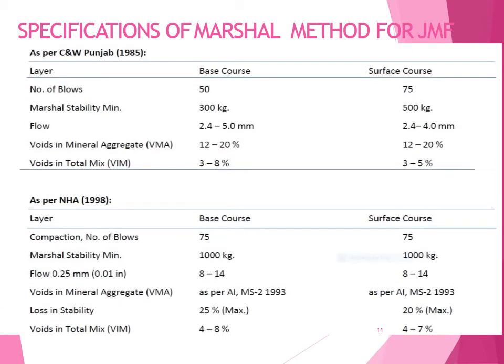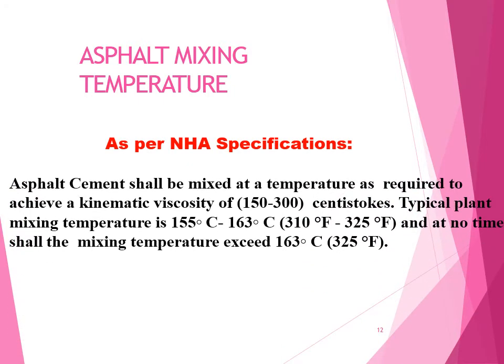Specification of the Marshall Method for the Job Mix Formula as per National Highway Authority: asphalt cement shall be mixed at a temperature required to achieve a kinematic viscosity of 150 to 300 centistokes. Typical plant mixing temperature is 155°C to 163°C, and at no time shall the mixing temperature exceed 163°C.